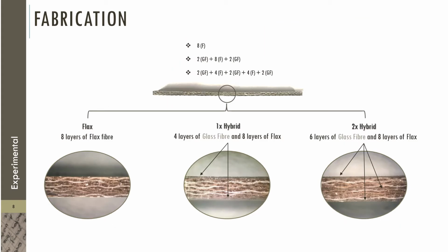In this slide, we can see the microscopic pictures of our composites. We can see the layers of the flax fiber, but also we can see, in the middle and the picture on the right, the hybridization of the composite with the 4 layers of glass fiber and 6 layers of glass fiber.